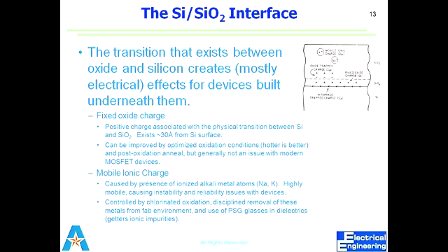It means every time, and this is the part where the diffusion process actually comes into play, because oxygen comes from here, it needs to diffuse through this oxide. At this point it will react, and the oxide thickness will increase. Okay, so after diffusing through here, the chemical reaction comes into play. So there is always an interface between silicon and silicon dioxide. This is actually called the silicon-silicon dioxide interface.